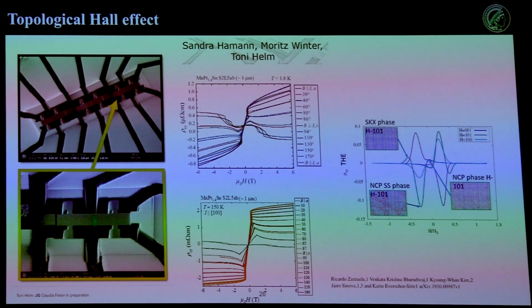And then what happens is, if you look through this, on the high field case, you have anomalous Hall effect, and ordinary Hall effect, and also planar Hall effect. But then when you get to lower fields, you actually see a couple features. You see this bump, which comes from this non-coplanar part, and then you also see this hysteresis, which is, you get this skyrmion that actually forms from an in-plane field, if everyone follows. Okay?